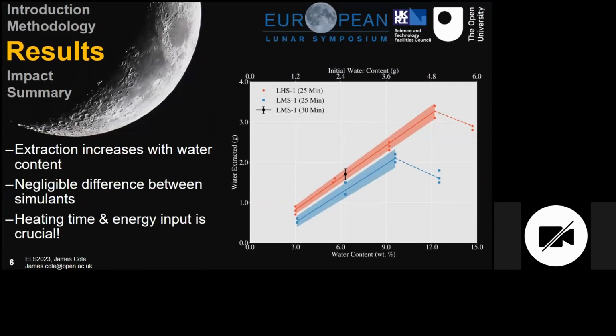So to the results. On your right, you can see a graph of water content along your x-axis and the water extracted in grams on your y-axis. The first thing to note here is that the Highland simulants and the Mare simulants seem to have different extraction profiles. This isn't quite true. When you're using the microwave system, there's normally an average absorbed power going into these samples, and for the Highland sample, we were able to get a higher average absorbed power. So when we were heating them for 25 minutes, the actual difference in input energy was significant.